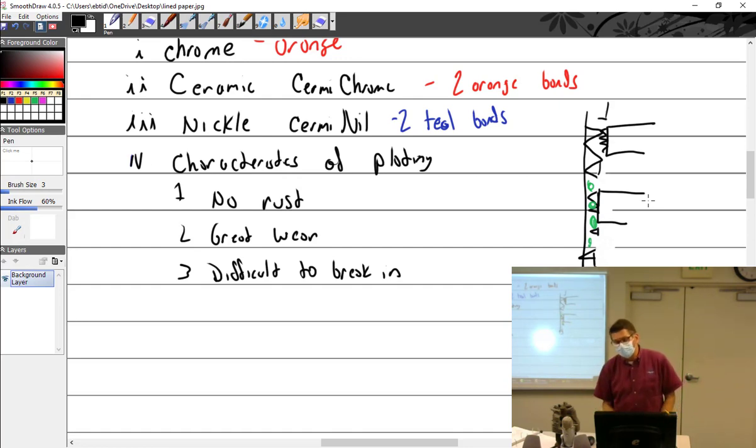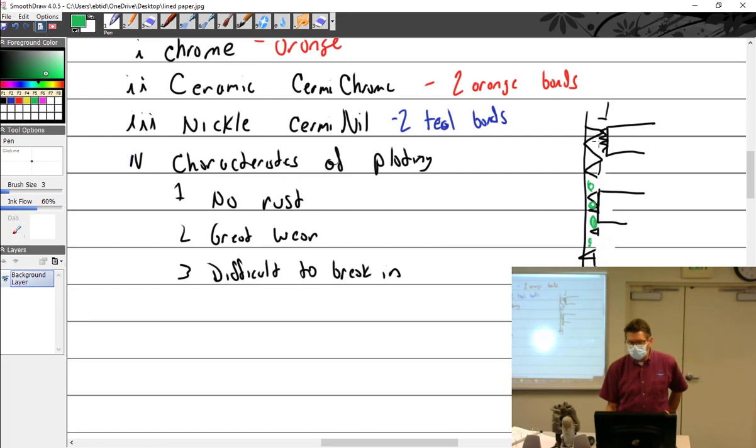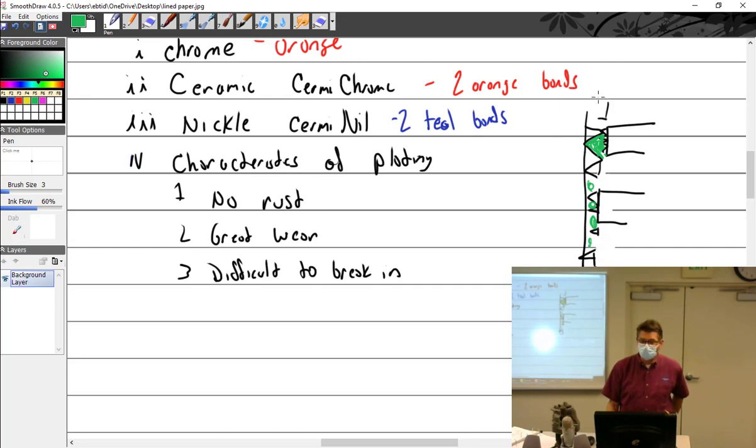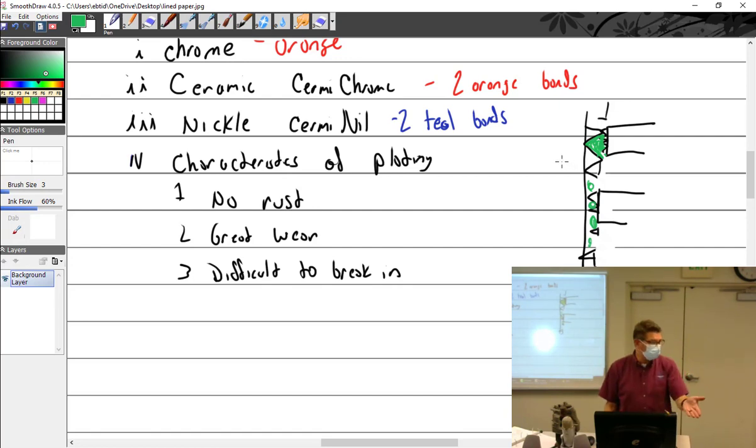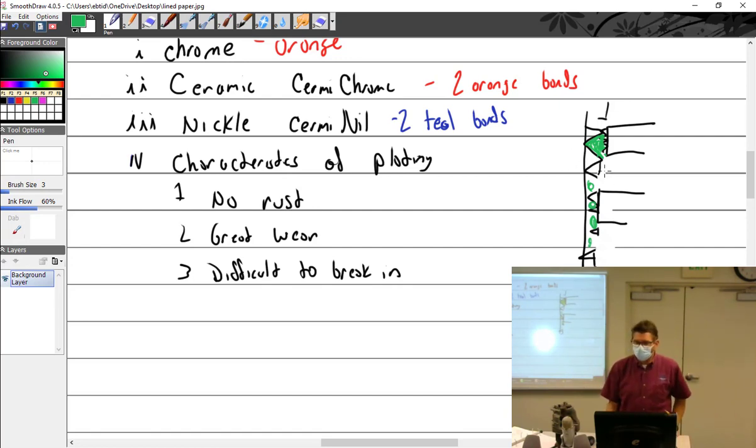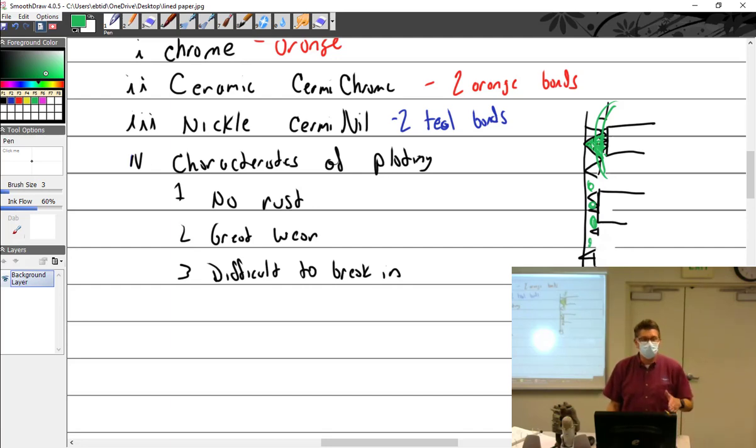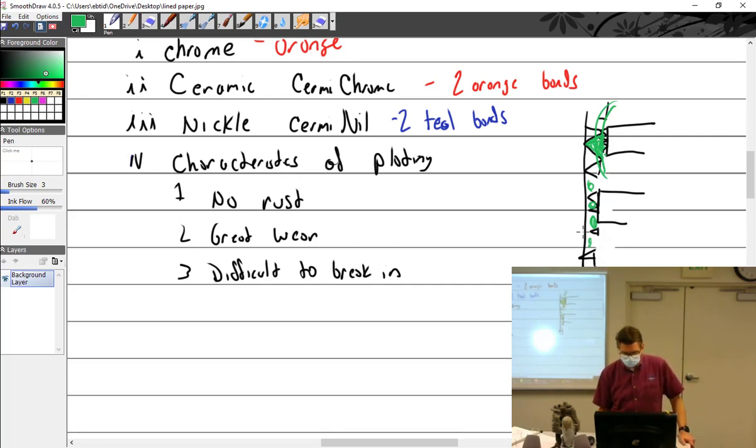So that's breaking in. We had a hard time breaking in these cylinders because they were so hard. Or if you didn't do it right, you kind of blew it. What can happen if you don't break in an engine properly? The oil is going to coke and turns into like a varnish, a very hard varnish surface.